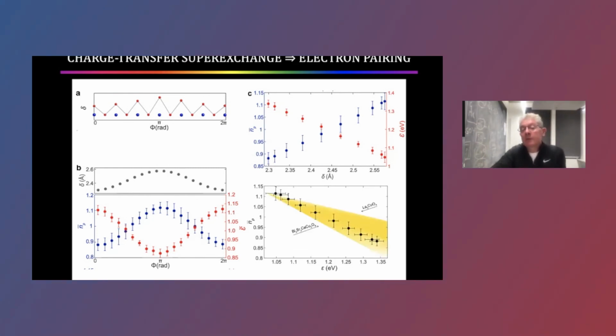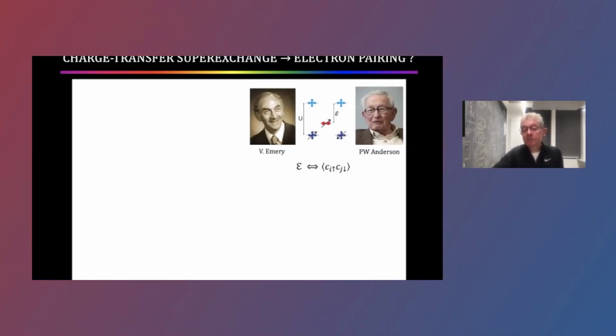Now, this fact, it turns out, is consistent with the theoretical predictions from the cluster DMFT calculations for hole-doped CuO2 using the Emery three-band Hamiltonian, which is an amazing fact, I have to say. We were startled, and so were the theorists. Okay, so here's the conclusion.